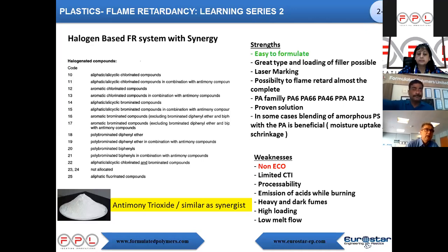So this is the strength, and don't overlook, it's a very well in use material, and it's still a living material. In some cases, we'll explain, there is a trend to phase out those brominated systems due to ecological concerns. In some cases, they are very difficult to phase out because the carrier of this bromine in the formulation is very often an aromatic ring. It can be polystyrene, for example, and it brings a kind of amorphous phase in the compound, meaning in some cases it reduces slightly the moisture uptake, and it gives a more isotropic shrinkage.